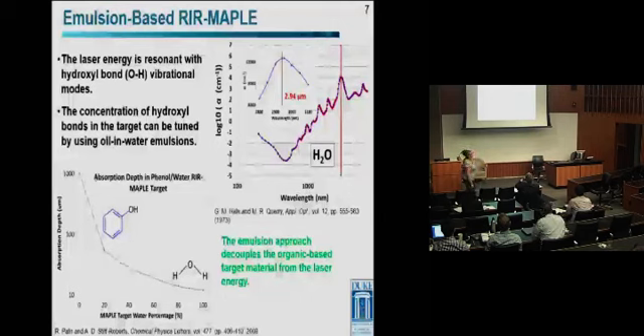Another important part then, since the laser is resonant with these OH bonds, we can tune the deposition regime that we are in. So if we have very few OH bonds, for example, using phenol as the matrix instead of the water emulsions, then we get much more actual splashing of the target onto the substrate. You can get really rough films, which might be useful for something like a gas sensor. A lot of the work that we've been doing is related to organic solar cells, in which case you want to have a very smooth film. And it's better to get into this regime where you have more OH bonds present. What's defining the difference between these is the laser energy density in the film. So basically, if you have more OH bonds, you have a higher laser energy density, and you get more evaporation of your target.